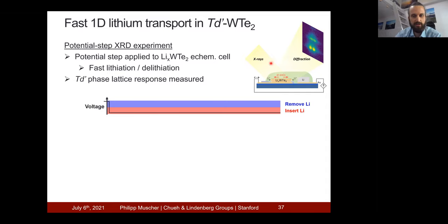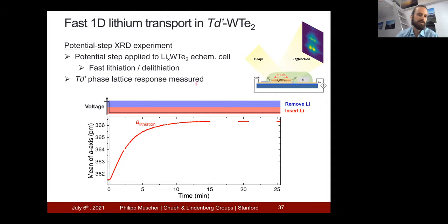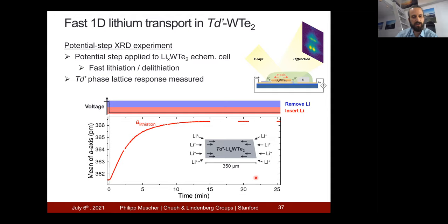Again, using X-ray diffraction. However, now we're looking at the entire flake, not just the edge. So what we're measuring is a volume average over the entire flake. From this diffraction, I can deduce the A-axis lattice parameter. And you can see that after the step of the voltage, that A-axis lattice parameter evolves quickly from one end state to the other end state. Within roughly 10 minutes, that transition is completed. And this is extremely fast considering our flake has a lateral dimension of 350 micrometers. And I can show the same thing for the delithiation, which is a very similar curve.